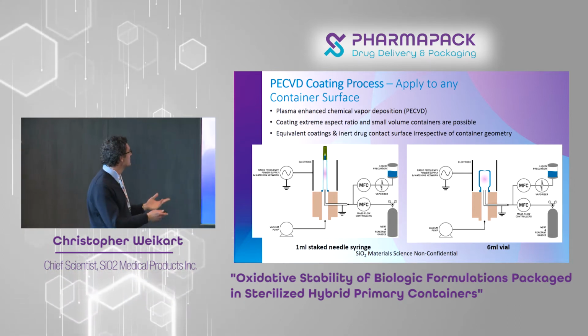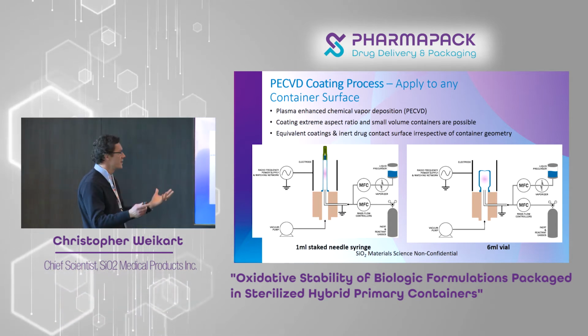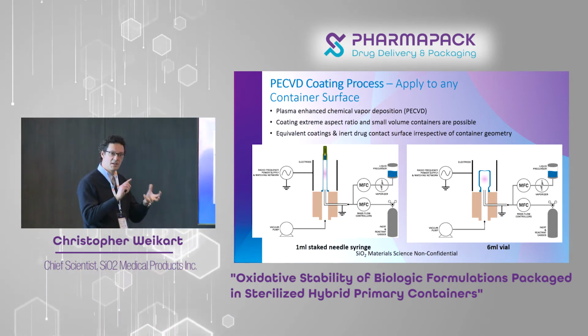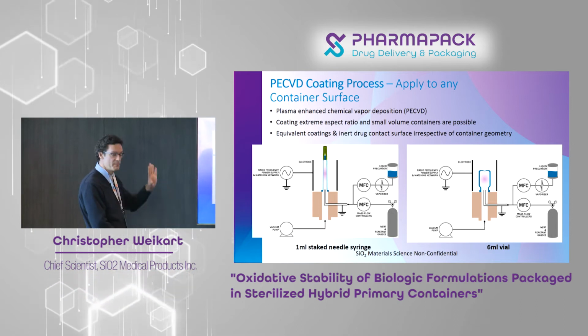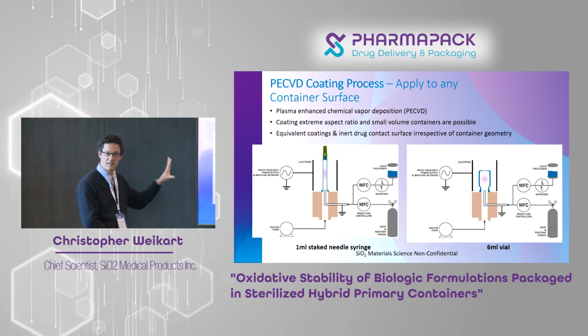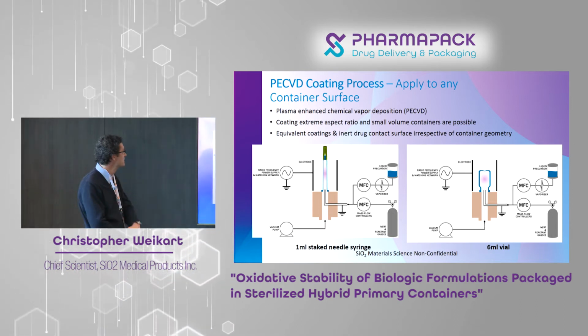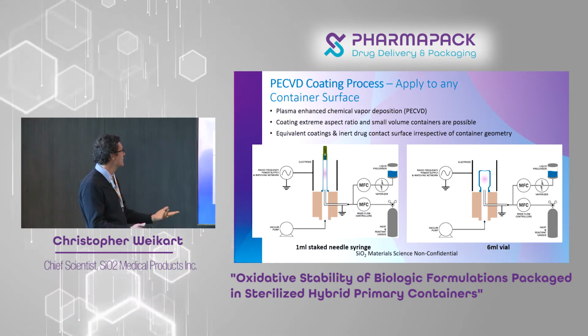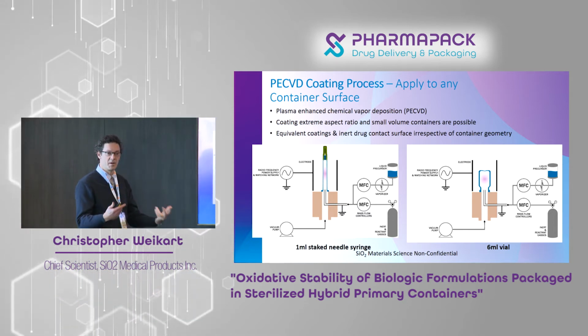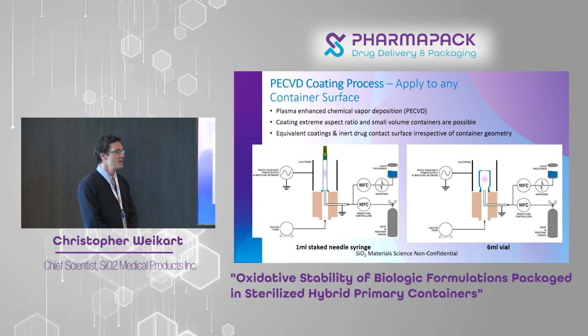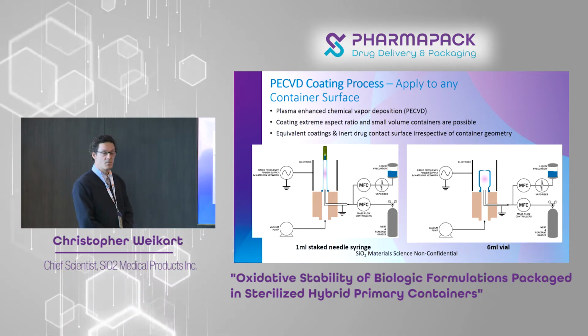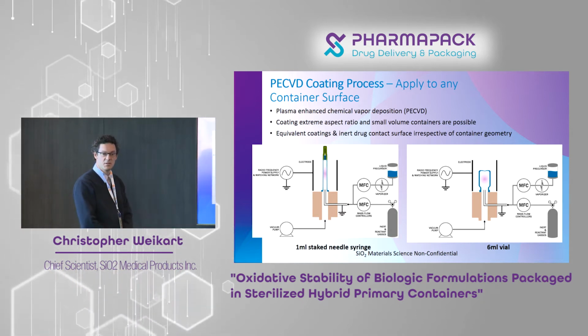But irrespective, you can coat very extreme aspect ratios, very odd geometries with it. We have a lot of patents on the technology that cover a lot of this on the process side and on the inspection side. And you get a coating that's highly inert, won't interact with the drug product, and it's consistent. The entire interior is coated uniformly.